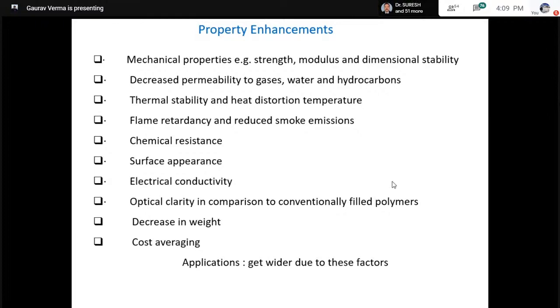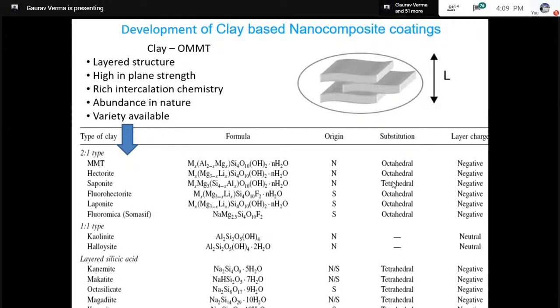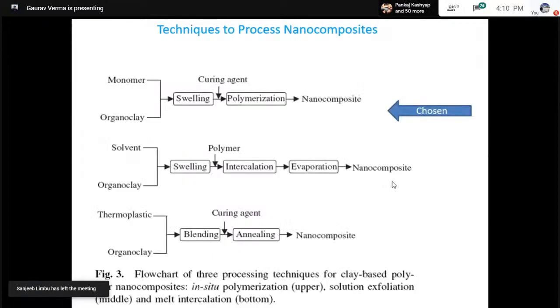Now, what really functionalizes these materials is the rich chemistry of these clays, because the clay is a simple ceramic, but if you really want to look deeper into its chemistry, it is really promising, as you can compatibilize these nanomaterials with any polymer matrix you want to include them into. So with this promising feature, we wanted to synthesize polymer nanocomposite coatings. And what we selected was polyurethane, because polyurethane is one of the most popular formulations which are used in automotive coatings. So what we wanted was to use the same polyurethane by introducing a very small portion of 2D nanomaterials into it and forming a nanocomposite.